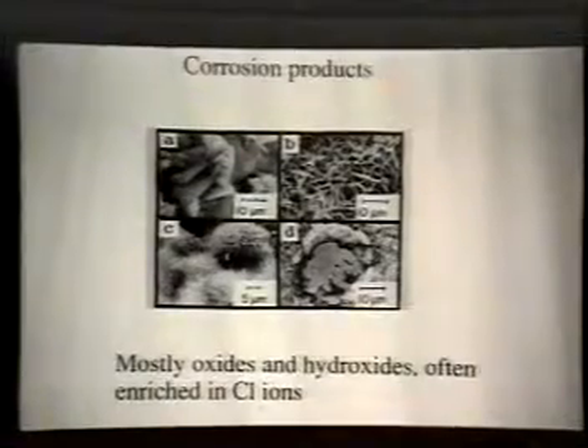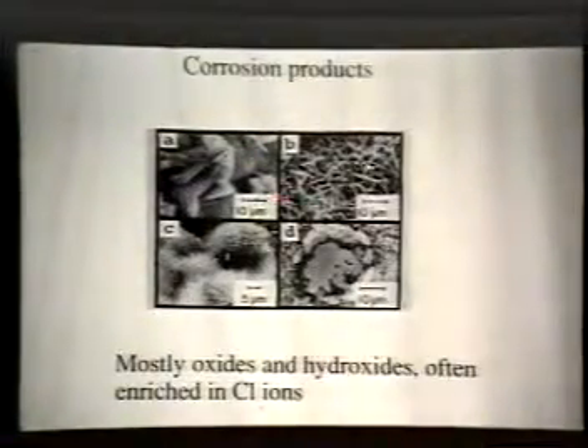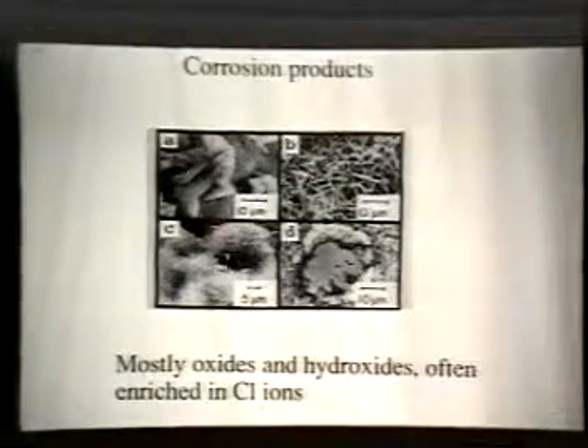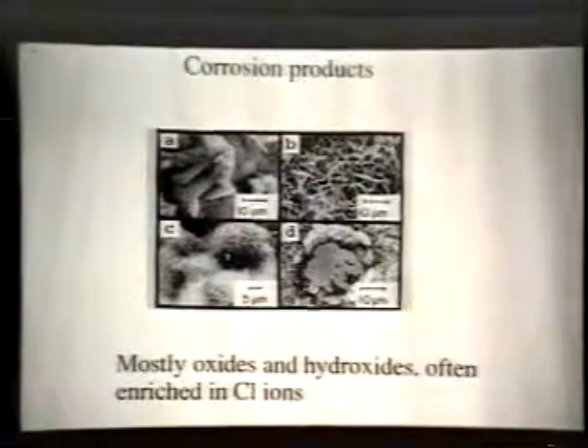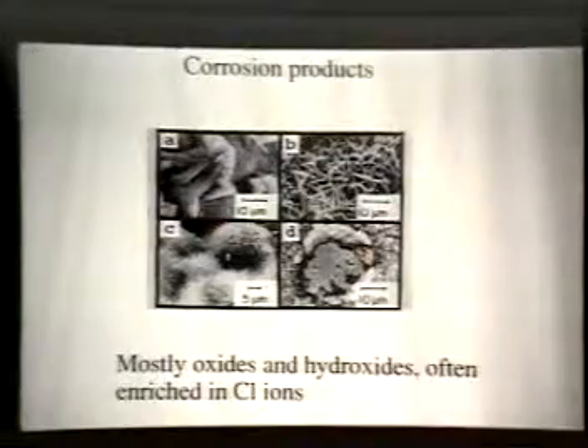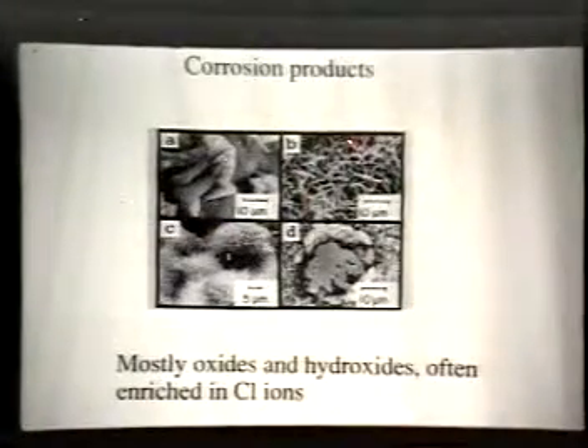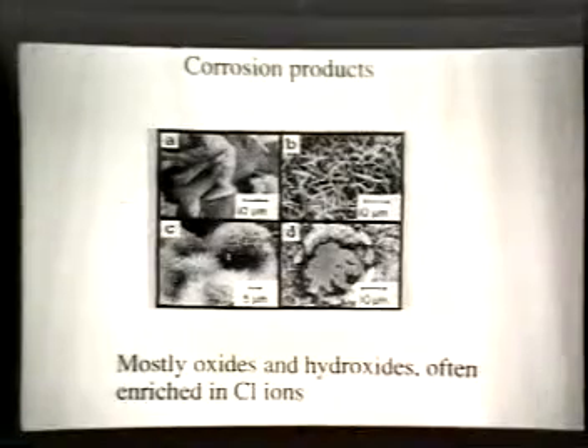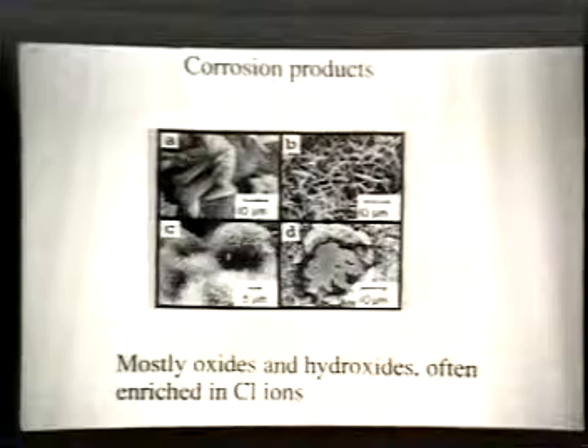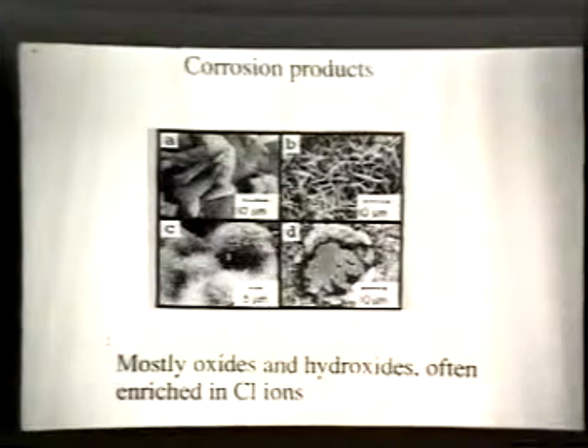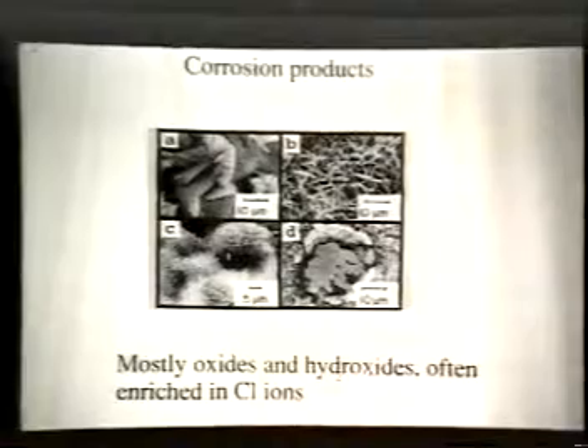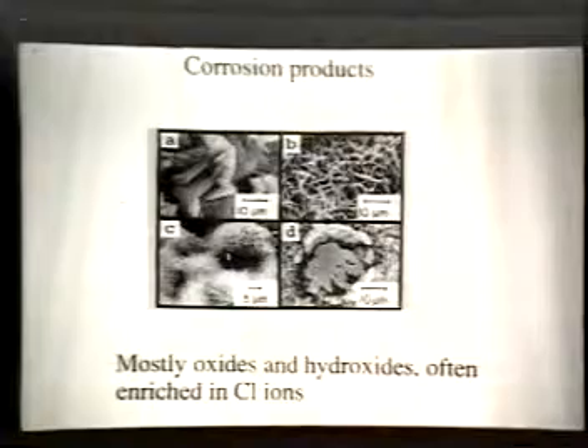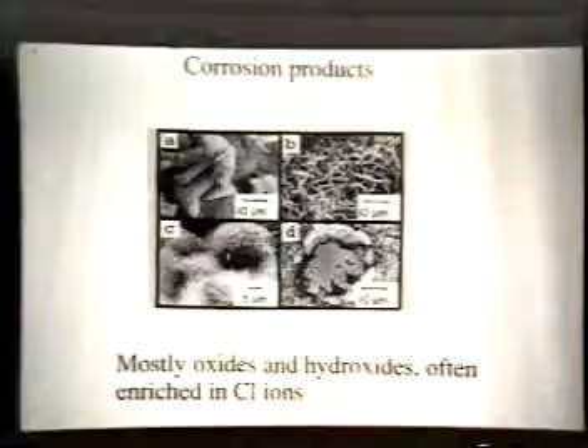Some of the corrosion products typically look like this. You have the tabular crystals, you have the lamellar crystals, which I showed you, and you have the delicate whiskery globular structures, which break upon exerting mild pressure. These are the types of crystals which cause major problems, exert a tremendous amount of pressure, and therefore cause disintegration of the concrete at the rebar paste interface. They are mostly oxides and hydroxides of iron. They are often quite rich in chloride ions, maybe from the de-icing salt, or, if it's a marine structure, from chloride ions from the sea.